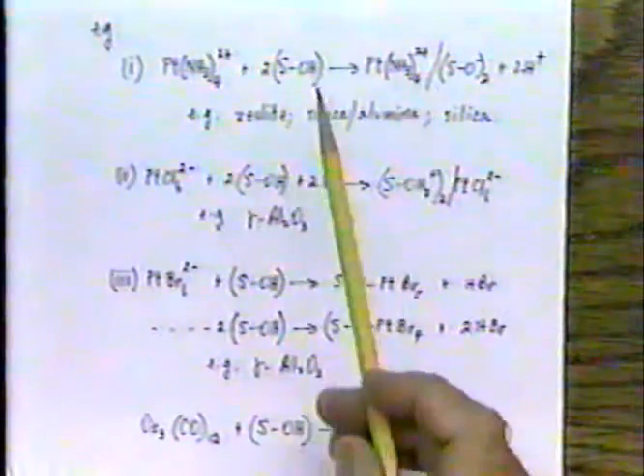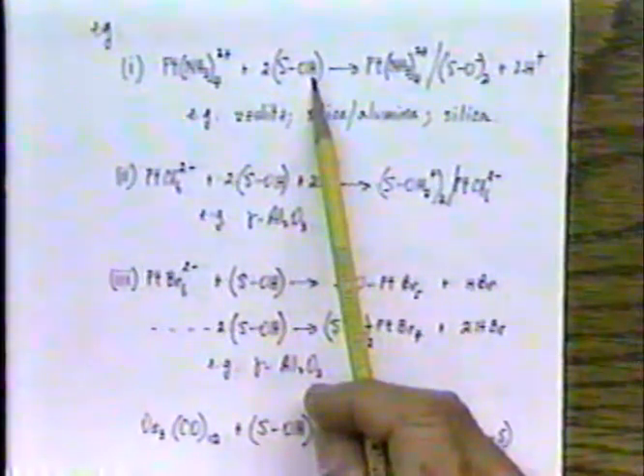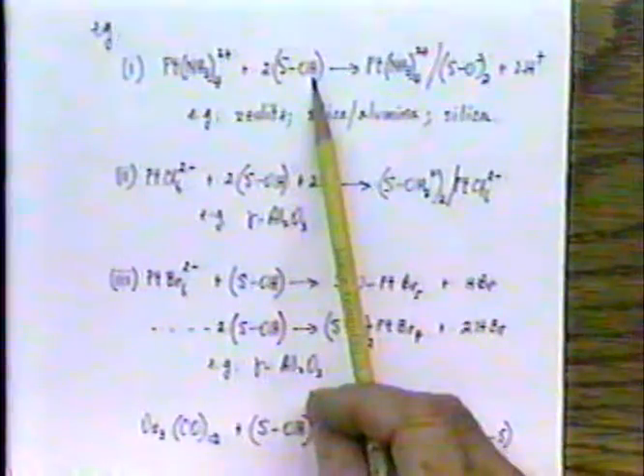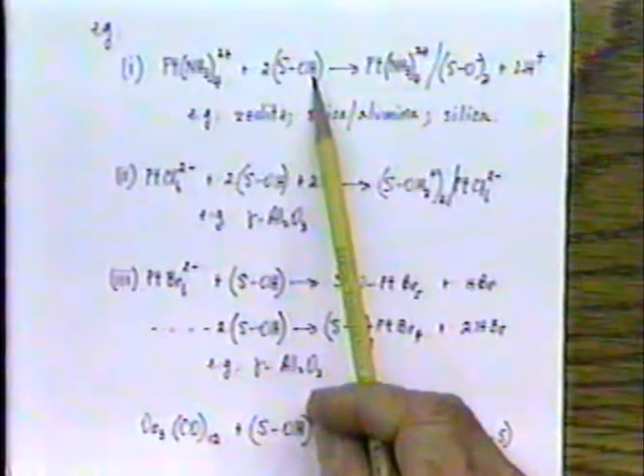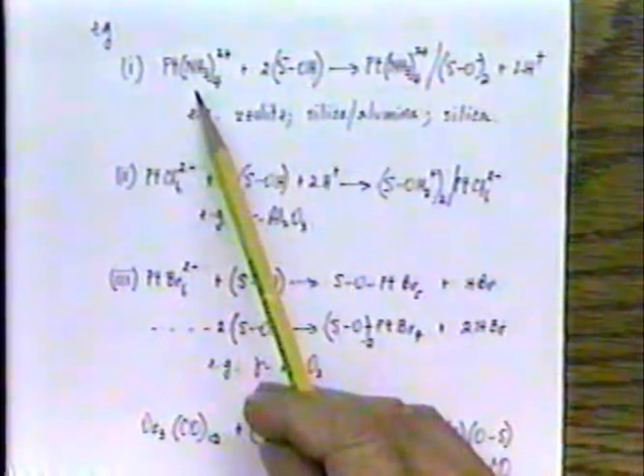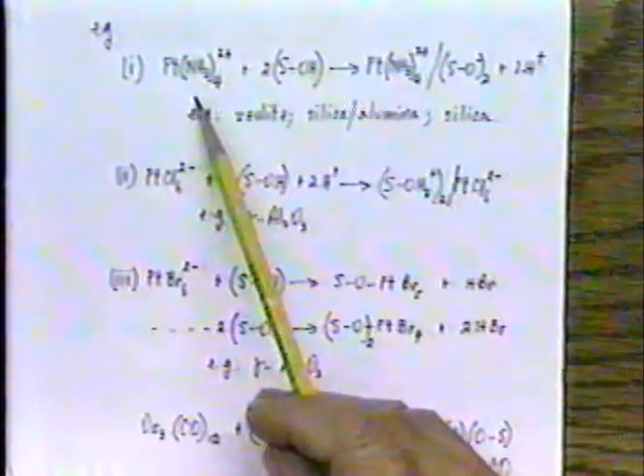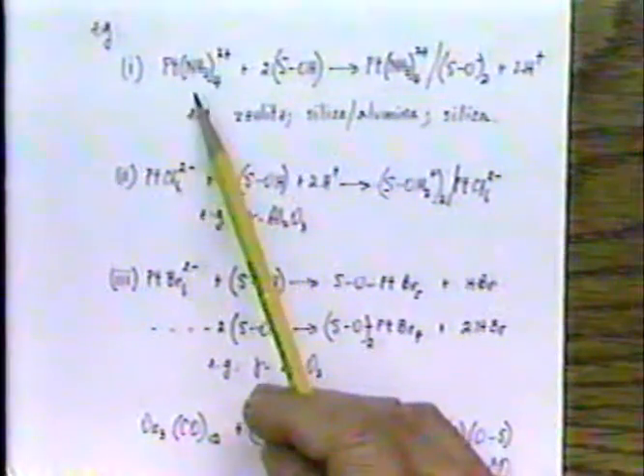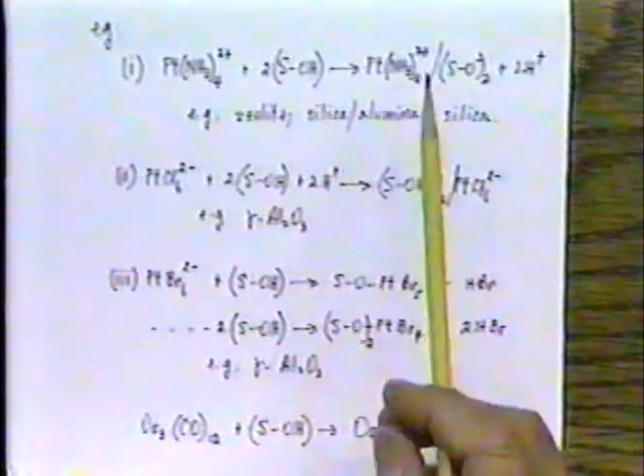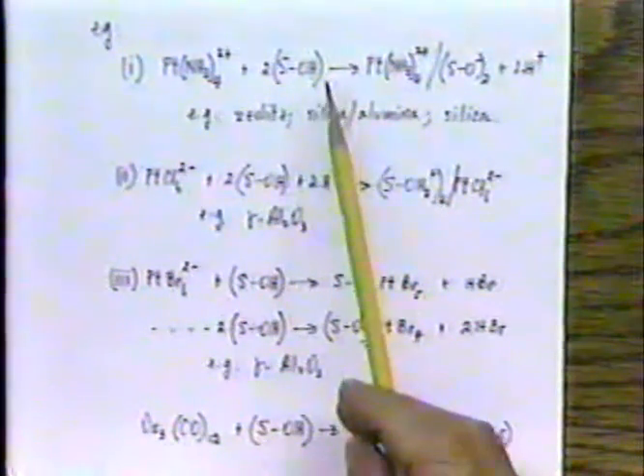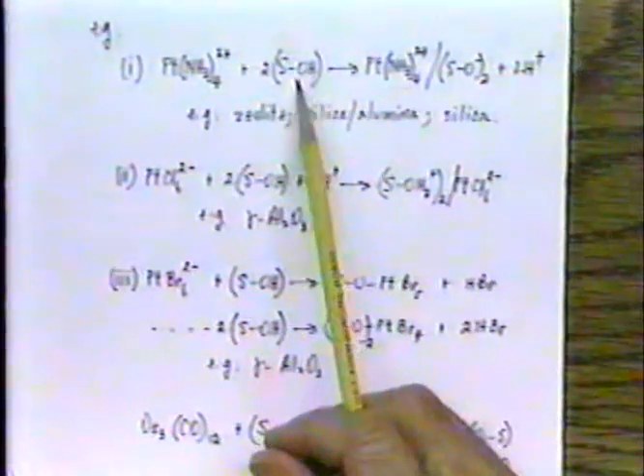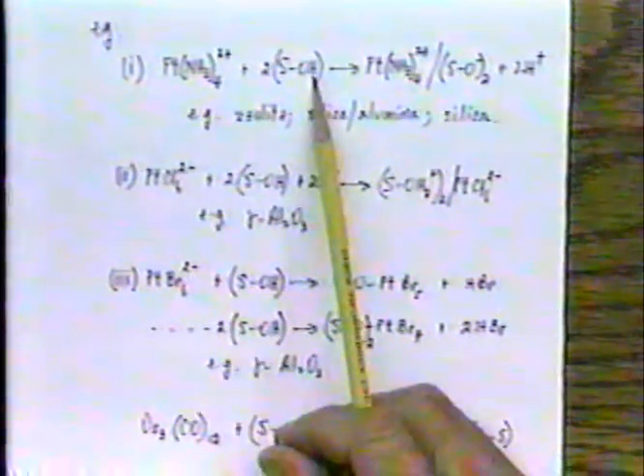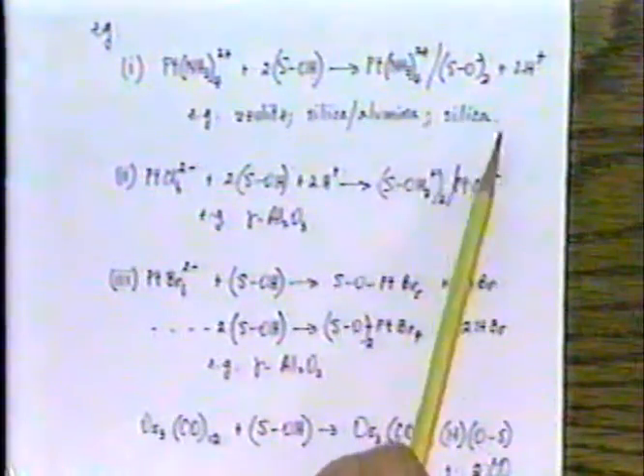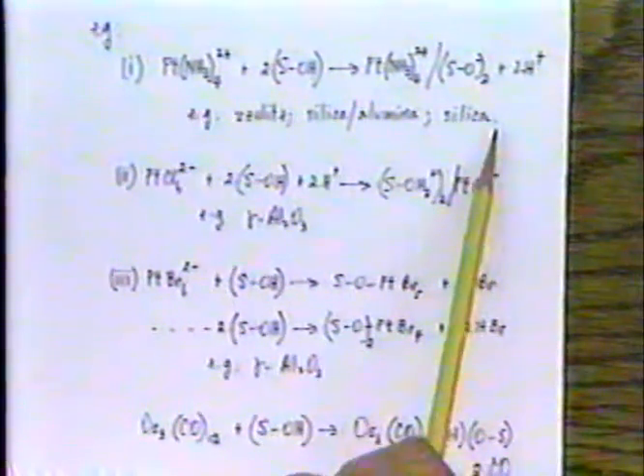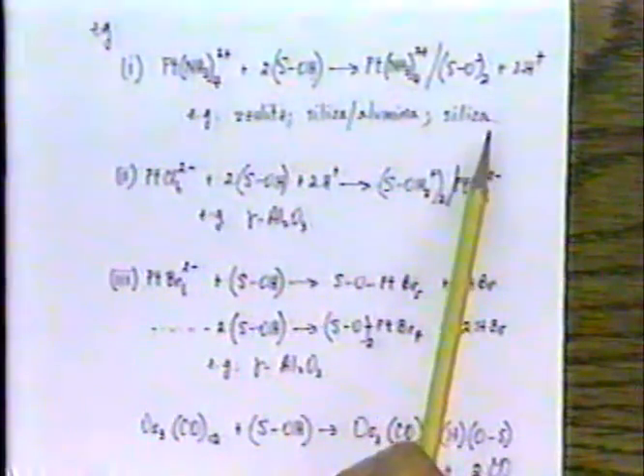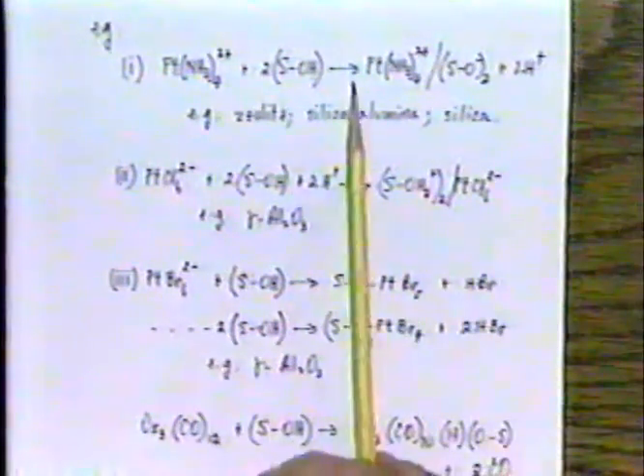In practice, I might point out that it's not uncommon to first replace the H by, say, a sodium ion, and then exchange the sodium ion with the platinum tetramine. But that's a minor matter, but you can understand the principle nevertheless. Typical substances in which some of the OH groups at least are acidic are zeolites, silica alumina, and even silica itself has surface OH groups that have some degree of acidity and which can undergo an exchange process of that sort.